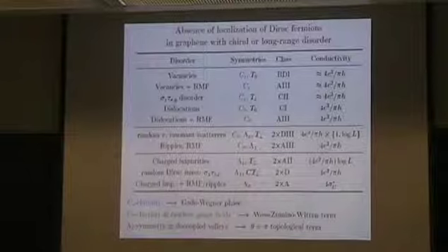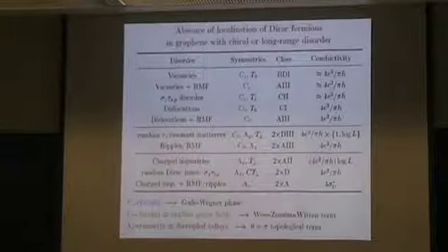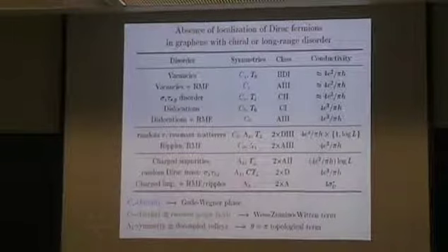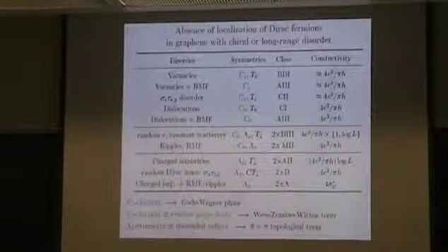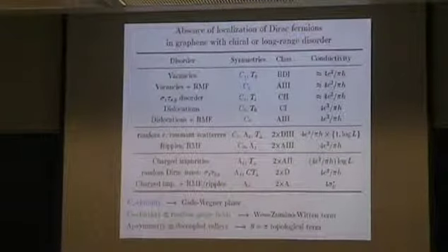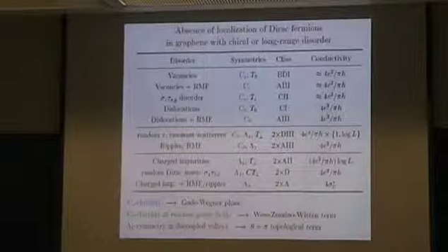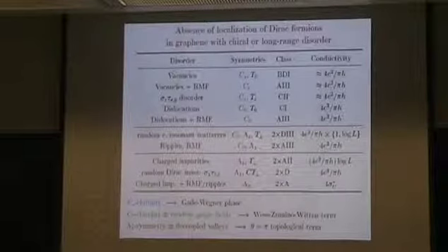And as I was talking about, was the situation where the symmetry, which is called here lambda z, just means that the corresponding component of the isospin is conserved. In physical terms, it just means that two valleys are decoupled. So the disorder does not mix the two valleys, so you can consider just one species of Dirac fermions separately from the other. And then there are still several possibilities depending on what type of disorder you have. You may have a random potential, random vector potential, and random mass, a combination of them. And so depending on this you get different theories.